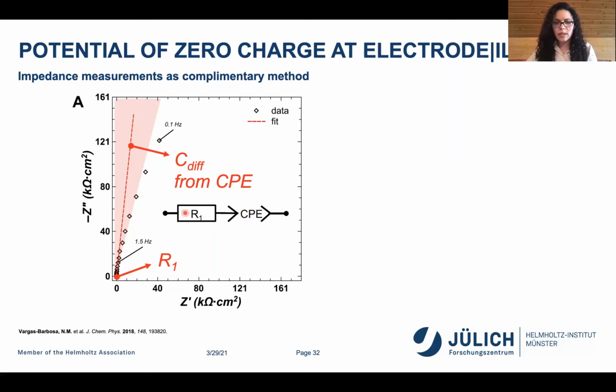The resistor is meant to give you the resistance between your reference electrode and your working electrode, and it reflects the ionic conductivity of your electrolyte. Whereas the constant phase element from up here is meant to give you the differential capacitance. So you can use that to establish the capacitance of the system, or the double layer capacitance. And so we do that, but you can see already that if we do that, we don't really get a good fit. So this is the fit if we do that, and all of these points at lower frequencies don't really get captured by this fit.